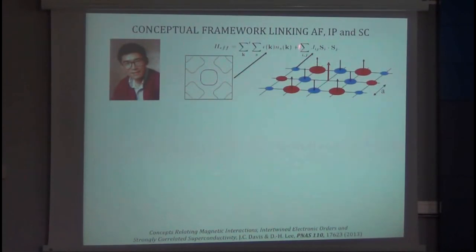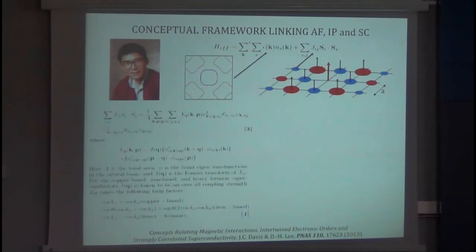The second term in the Hamiltonian is on-site antiferromagnetism. If you put an electron at one site, and if you bring a test electron up to a nearby site, what does it feel in terms of the magnetism? So if your original electron is spin up, on-site antiferromagnetism would produce spin down at four nearby sites, spin up at four second nearby sites, and so on. And you can parameterize that by a number, the exchange energy, you can call it, or the magnetic energy, and S_i dot S_j, where that's the spin on each site. That's a really simple Hamiltonian.